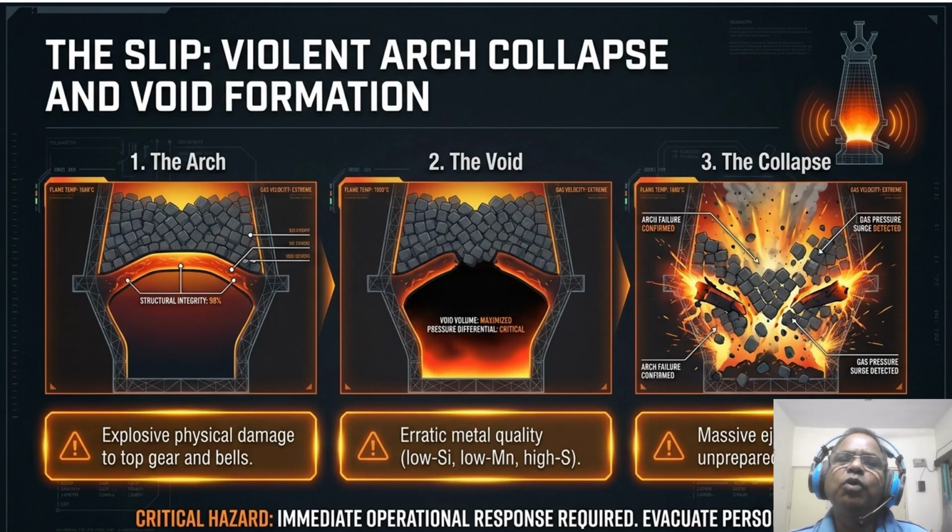However, for a cold hang, the cause is viscous, solidified slag clogging the coke grid, often from a leaking cooling plate. The intervention here is to raise the blast temperature. So look at the warning at the bottom. Misdiagnosing the thermal state leads to opposite action, which will accelerate system failure. If you add heat to a hot hang, you will fuse the burden into a solid mass. If you take heat away from a cold hang, you will freeze the hearth.